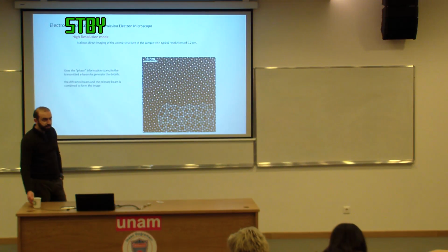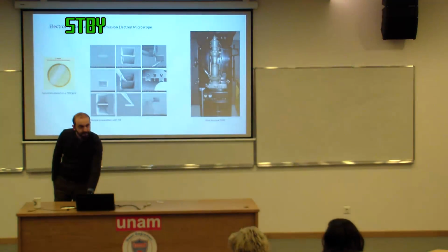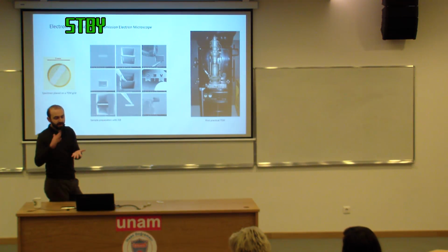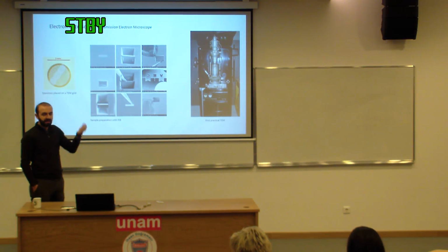Maybe you have talked about it, but my question is, is there any specific sample preparation for TEM and SEM? I mean, it depends on what kind of material you want to study. If it is a biological sample, there are different techniques. You embed it in a polymer matrix or things like that. You take slices out of it, very thin slices, a few hundred nanometers thick. We have a machine called an ultramicrotome, which takes very fine slices. You put it on the TEM grid, you go downstairs, it goes fine.